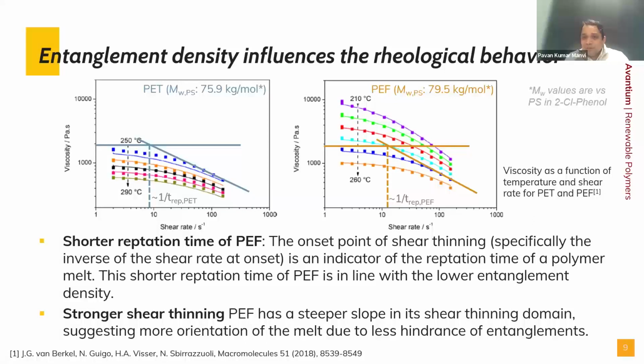And what is the use and the implementation of this reptation time? So we understood PEF has a lower reptation time. So if we apply some heat or shear, then it should mobilize faster. It means the polymer chains of the PEF. And if the polymer chains are mobilized faster, that means the change in the viscosity will be faster than PET, which we see also in the curves, that the distance between the different rheology curves is higher than in case of the PET. With the increase in temperature, the viscosity goes down faster than PET.